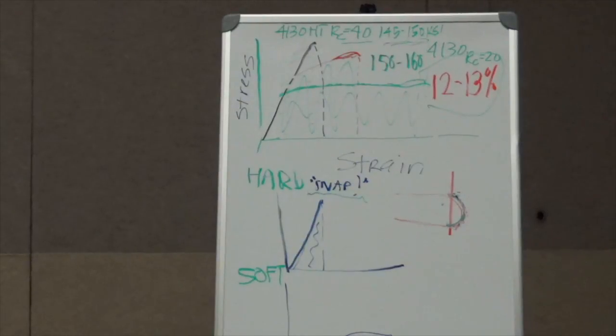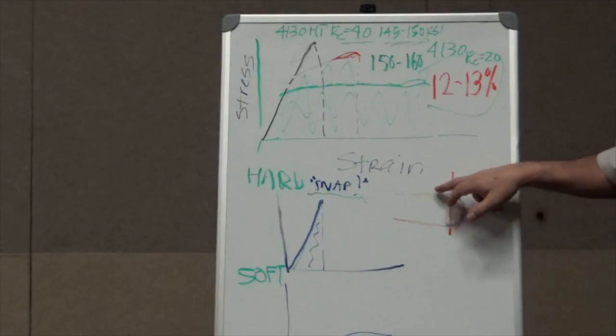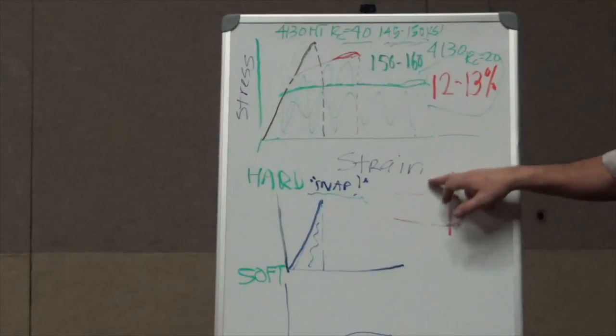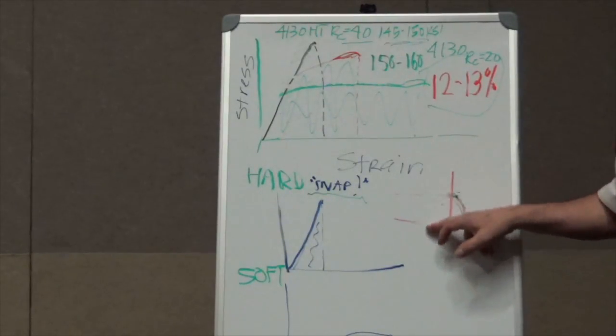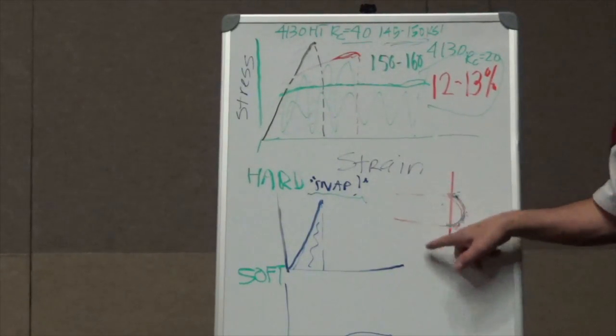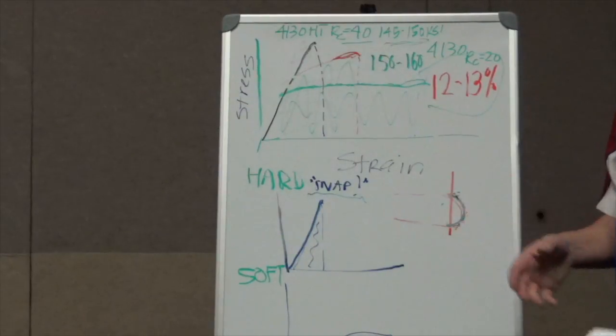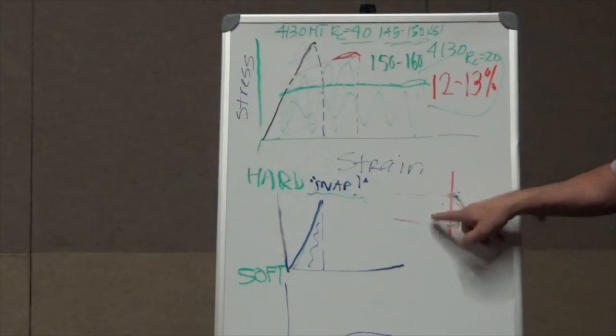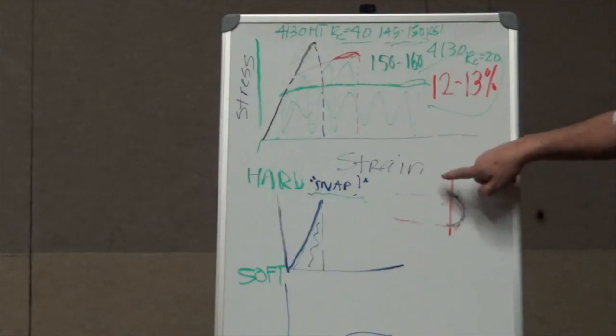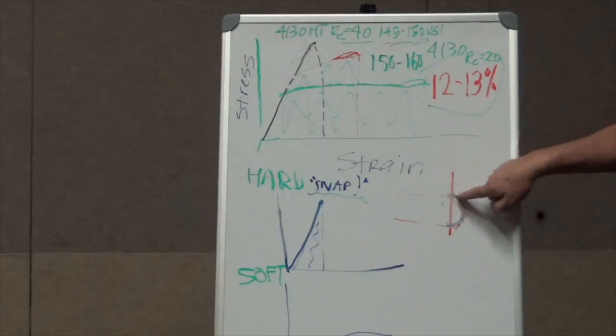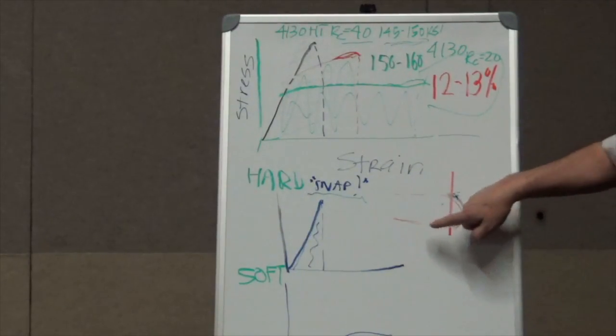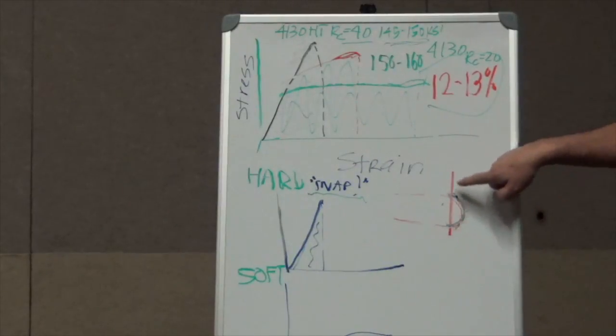The other kind of odd secret that we discovered was that where we thought the heat affected zones were out here, let's say, where you see your blue lines, when you weld them, none of the tubes fail. Why is that? It's because of geometry. It has nothing to do with the material. It has to do with the idea that where these tubes are joined is where the stresses are the highest, right on the edges of those welds.